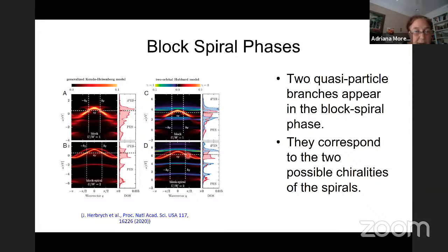Here we get 2 quasi-particles that are degenerate only at the center and at the boundary of the Brillouin zone. These 2 quasi-particles correspond to the 2 possible chiralities of the spirals, which can go in one direction or the opposite. These states appear in the 2-orbital Hubbard model, and also very clearly in the Kondo-Heisenberg model. This is a very interesting development.